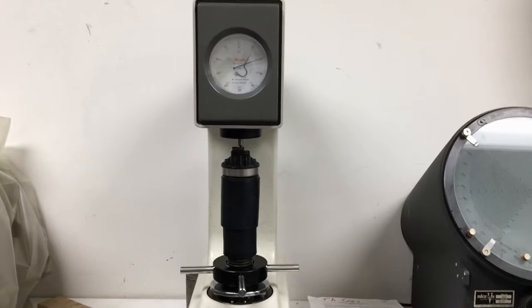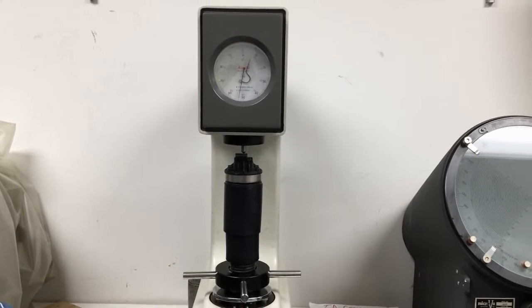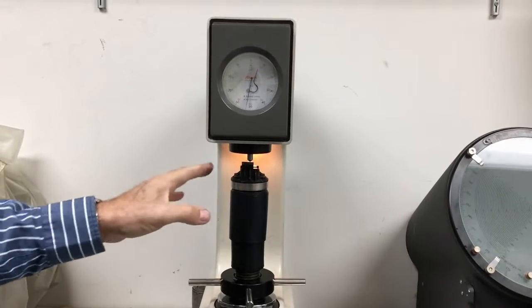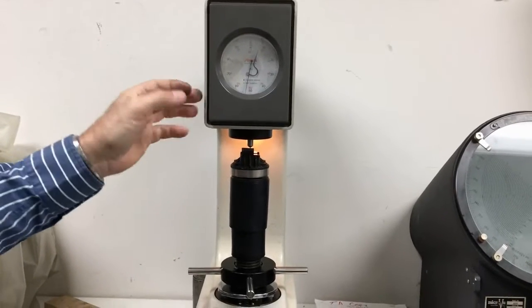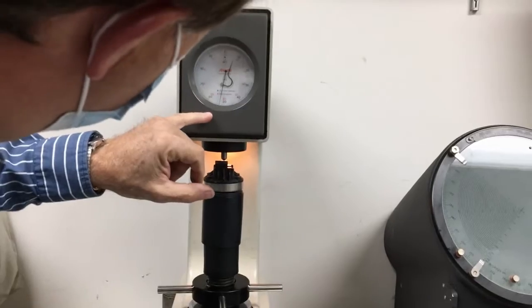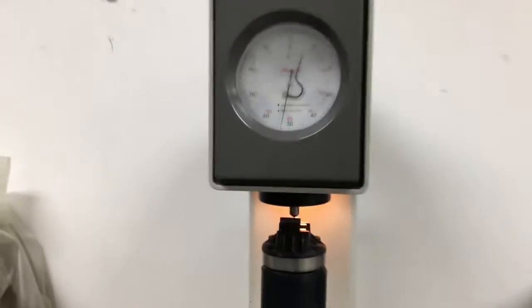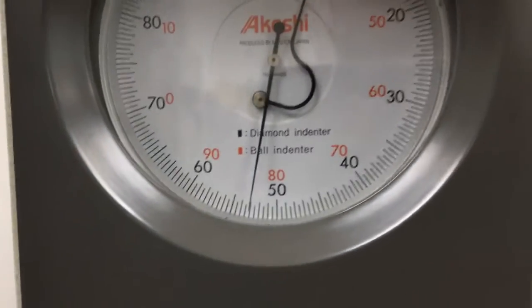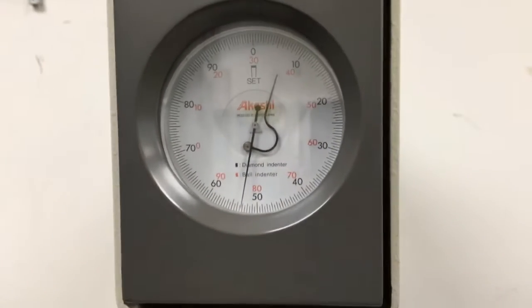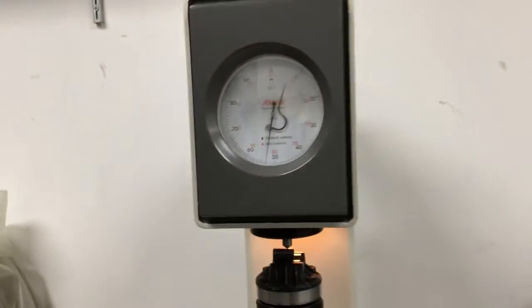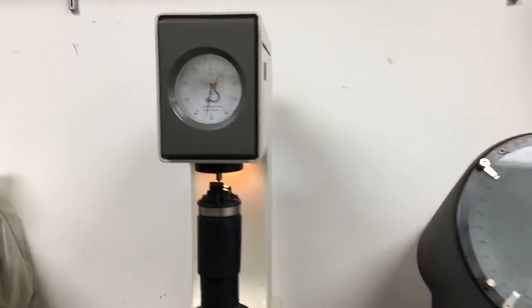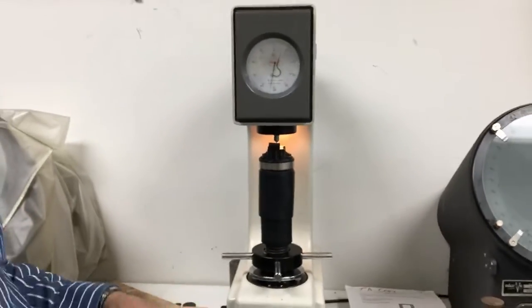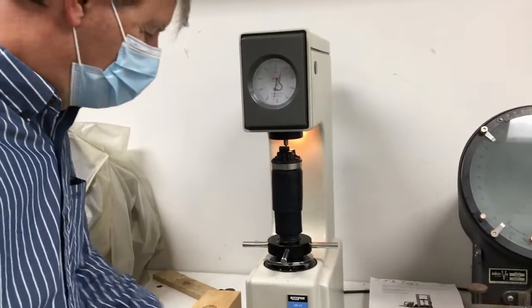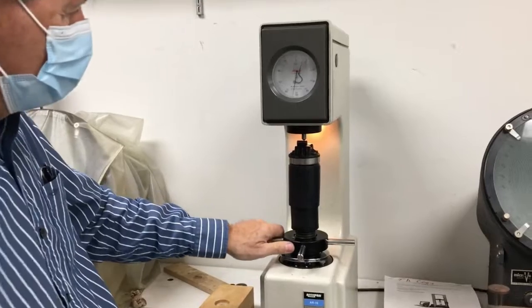Originally this was about a 10 to 12 Rockwell. After heat treating and then removing the scale, we now have about a 53 Rockwell C scale, the outer scale, the black scale, about a 53. So we increased from 10 to 53, about 5 times. We really saw a lot of hardness in this part.